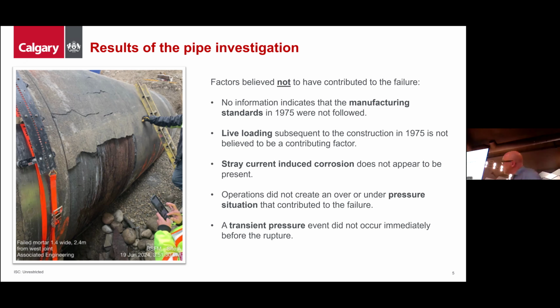Steve, please. That picture, the cracks in the mortar layer, is that as you found it, or is that because you've excavated? So actually that is found on site. And that's a great question. I can't answer your question, Nigel, if it's because it was unearthed and it spalled, or was it in place? My guess is actually it spalled after we started unearthing, exposing the pipe itself, and it just started falling off. The reason I suspect that is we had that occur at another location, just at Crowchild Trail, a little further down, and I can give you a little more information about that.